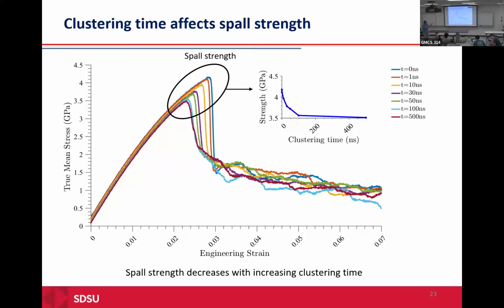But one of the things that we all neglect is talking about strain. You saw that ball goes through a lot of plastic deformation. That complicates things because when you have strain, you have a high mechanical energy. That mechanical energy has nothing to do except heat. So now you are doing phase transformation in addition to the stress. You're actually changing the material in situ. So one of the biggest problems in molecular dynamics is that you don't account for all this. So you need an experiment that actually can induce such a high amount of stress with very limited amount of strain. There's only one experiment that can do that. Come visit my lab.